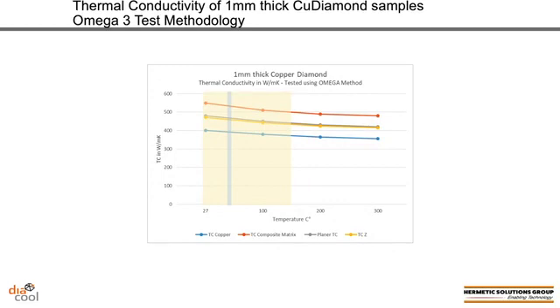So understanding that the structure of this material could have an effect on the testing of its thermal conductivity, the fact that it's not homogeneous from one edge to the other made me think that we needed to look at this a little differently. So I considered the Omega-3 test methodology that effectively takes a sandwich structure of material like this and breaks it down into its constituents. In the case of the chart you see here in front of you, I tested this material over a range of room temperature up to 300 degrees C. Again, that tan bar, or that tan box, kind of represents operating temperatures. So if you look at this chart, let's look at it from the bottom up.